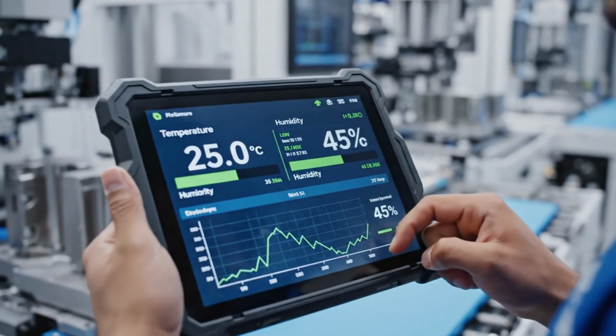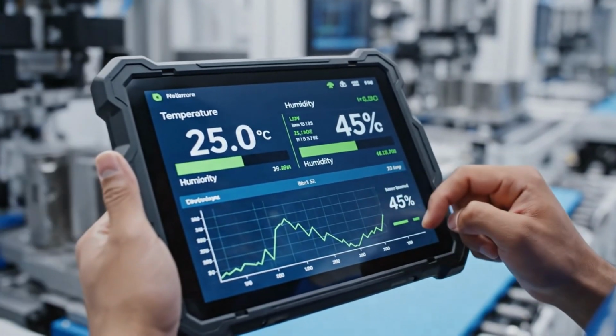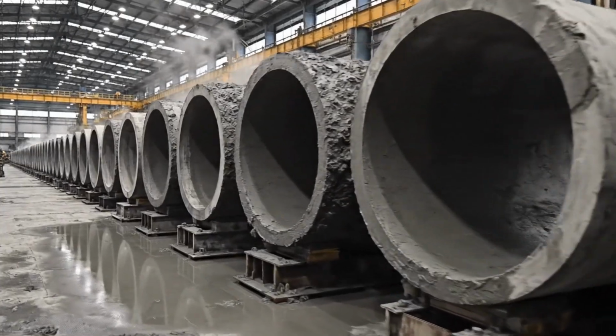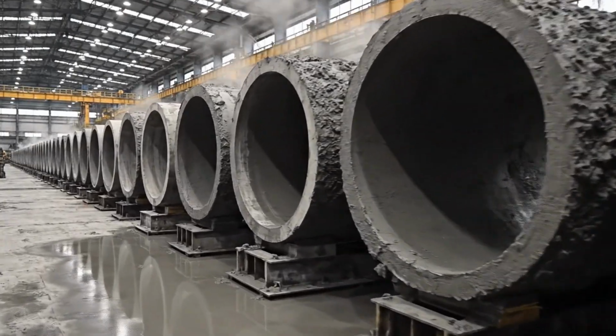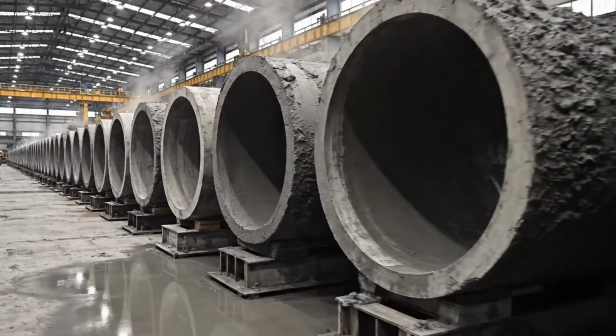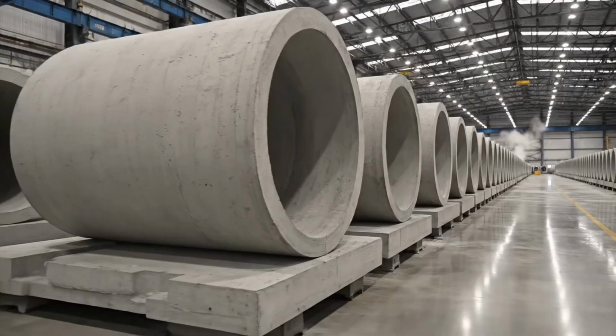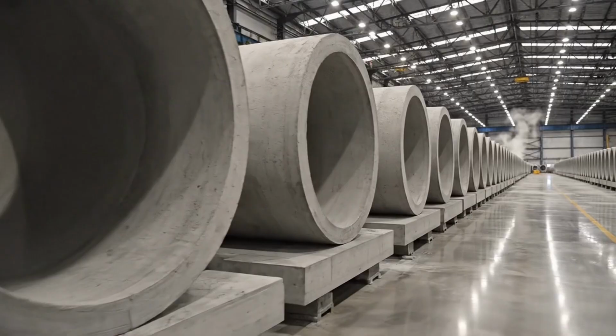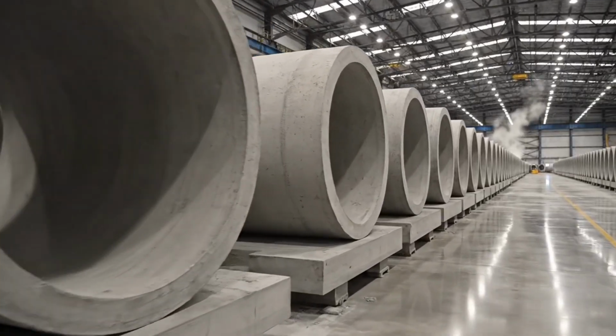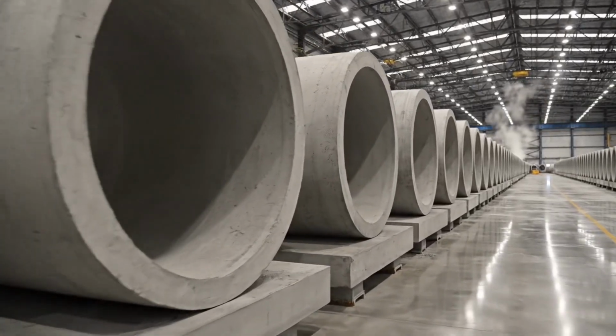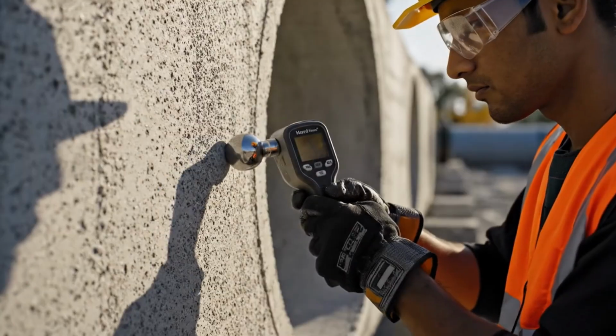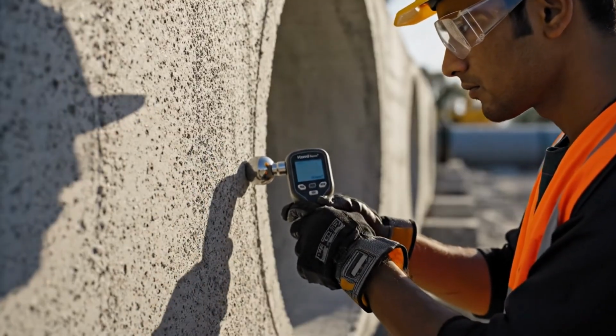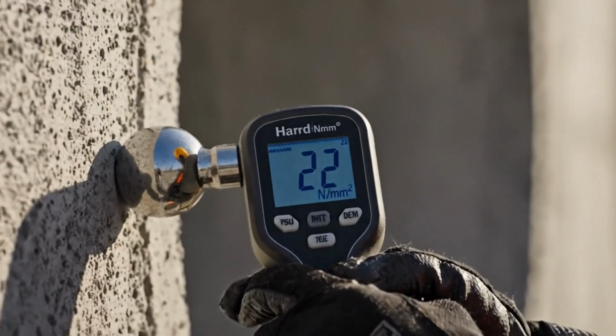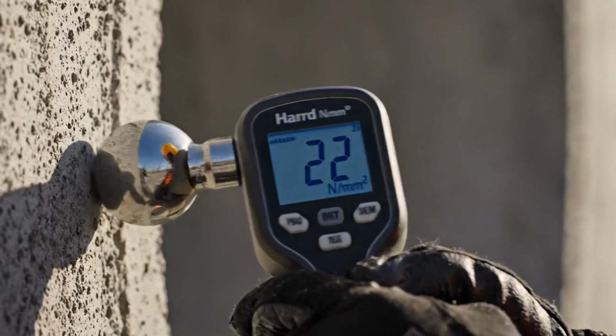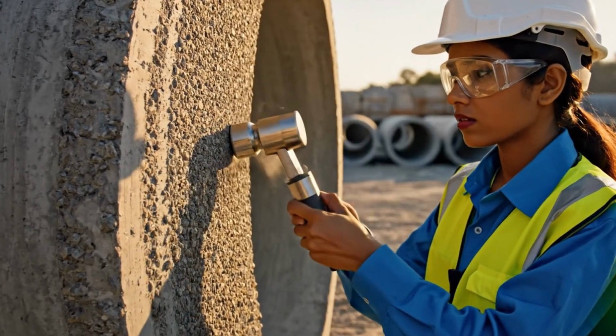Therefore, the exact moment of demolding depends on the mix, ambient temperature, humidity, and the behavior of the produced batch. After removing the outer mold, the pipe usually remains for more time on its base or in a controlled position. The reason is simple: it has not yet developed its full resistant capacity. Although the shape is already defined, the structure continues to mature. At this stage, any blow, torsion, or poorly executed lift can introduce micro cracks that are not always visible immediately, but that will reduce the useful life of the buried product.